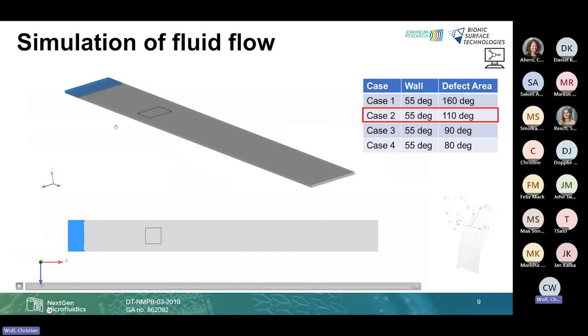Yeah. So that's typically a cross section of the sensing chip, as it is, for example, in the change speed chip, and maybe you have some sort of deterioration at the bottom where the contact angle is different than the surrounding matrix material, or you have a sensing spot with another surface energy. And with the simulations, you can, for example, investigate what happens when you fill that by capillary forces. And you can see here the result of such a simulation.